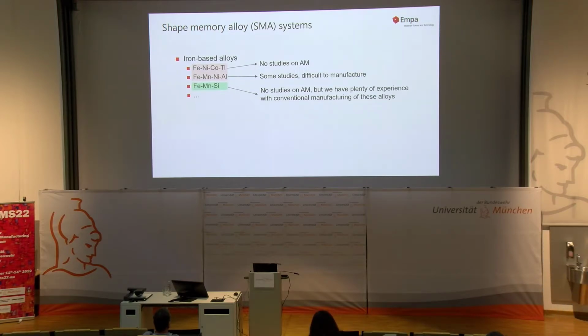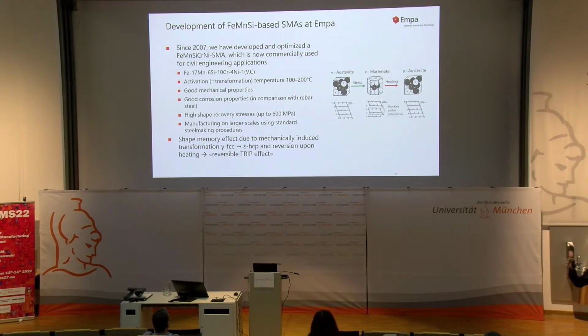But we at EMPA really have plenty of experience with conventional manufacturing of these alloys. Just to summarize what we did: I've been working with that material since 2007. We have developed and optimized such an alloy, which is now commercially used for civil engineering applications. Here's the nominal composition. Actually, there should be 5 silicon here. It has very interesting properties tailored for civil engineering applications as a self-pre-stressing rebar material. I will show you some applications afterwards. The shape memory effect in that type of alloy is the result of a mechanically induced transformation from austenite, gamma FCC, to the hexagonal type of martensite.